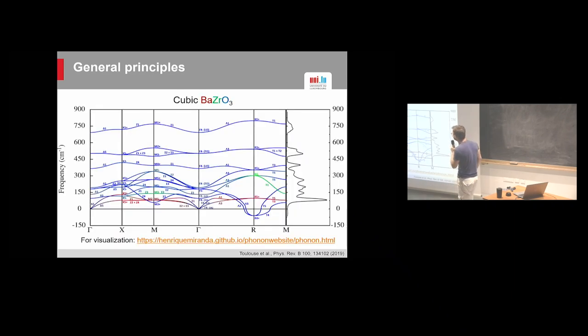Here is another example with a bit more information. So this is now barium zirconate. If you don't know barium zirconate, it's basically cubic at ambient pressure all the time, so pretty simple. But when you compute the phonons by first principle calculations, you always have a problem here. So not at the zone center, not with a ferroelectric mode. This thing is not ferroelectric at all. But you do have a problem here at the zone boundary with a mode that is slightly unstable, below 0, above 0, depending on which exchange correlation, remember that?